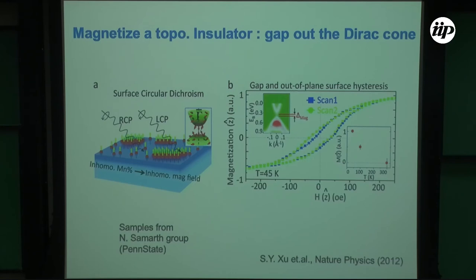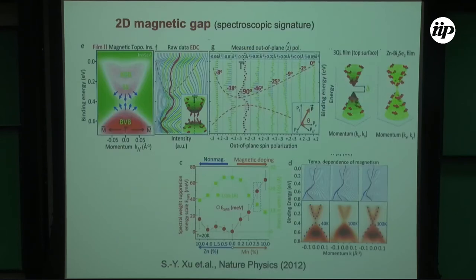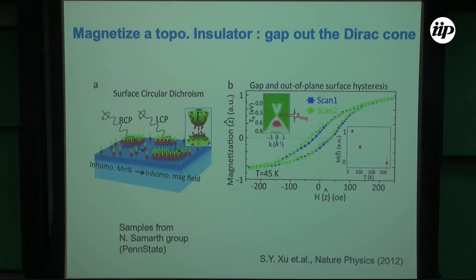But then the experimental diagnostic is that I'll show you in a moment. There can be gaps for other crazy reasons. And so that's why this coupling is very important, that we had to do in situ measurements of hysteresis and couple it to the gap. And then, of course, you can also look at the temperature dependence, right? If it is related to magnetization, when magnetization disappears, the gap should also disappear, and it's an interaction effect. So one powerful diagnostic is that, if you look at this image, it's not immediately clear. The no spectral weight means green, but in the middle, it's kind of still whitish. So it's not immediately clear. Is it a clear, clean gap or not? Or am I playing with the image color plot or something? Who knows? So in order to convince ourselves and convince you, yeah.